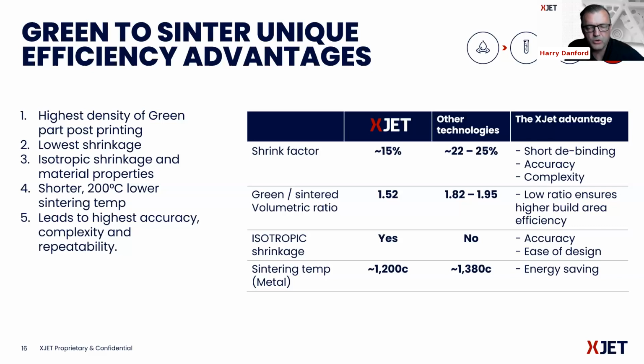Each material individually will obviously have its own dialed-in shrink factor, and we've dialed it into the 1/10%. So as an example, the 99.99% alumina is 14.5% shrinkage, and the stainless steel is more in the range of 15.5%. Other technologies will be in the low to mid 20s in terms of shrinkage, and generally not quite isotropic, again, generally speaking.